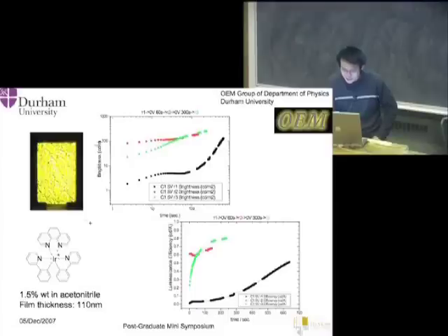You see, this is the charging time for the device, which applies only 5 volts. For the first 10 minutes, you see the light begin to grow gradually. But when you turn it off for 1 minute and turn it on again, it immediately has the same brightness as when you turned it off.